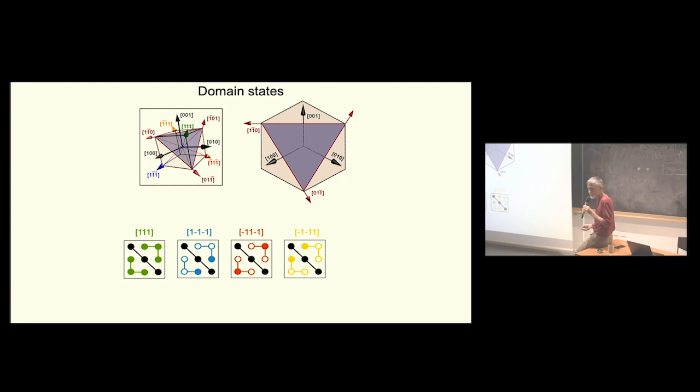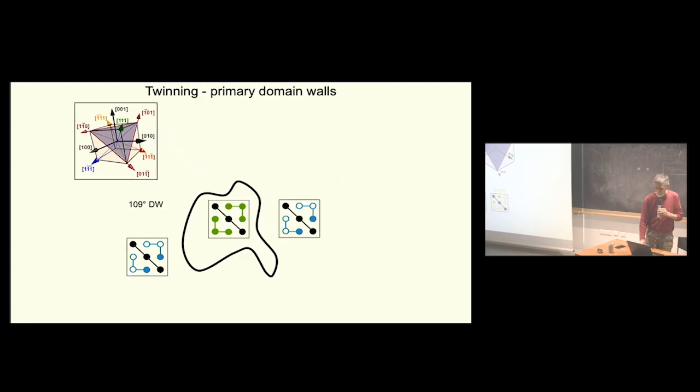So it's also the case where polarization cannot be switched by 180 degrees. The symmetry says that if you switch by 180 degrees, it's not the same thing, not the same energy. So you have only 4, you don't have 8, even though it's rhombohedral. Each one has a different strain, and one strain corresponds to one polarization, so it's one to one. It's fully ferroelastic, fully ferroelectric.